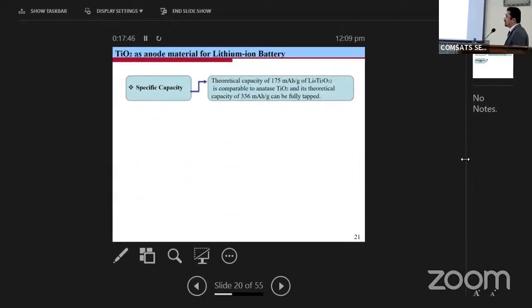Its specific capacity is comparable. You can see that lithium titanate has very good safety. The safety issue you can solve with the help of lithium titanate. And for capacity, carbon has a good capacity, 372 milliampere hour per gram, the capacity of graphite. So I try to enhance its specific capacity and also enhance safety. I use this structure in nanomaterial, and I achieve this, and its capacity is 336, which is near to 372. You cannot say 100%, but near to. It's better than lithium titanate, and its safety is also better than lithium titanate.